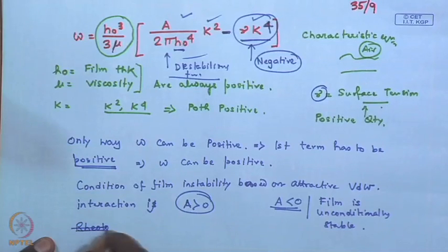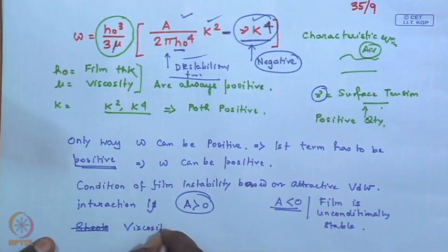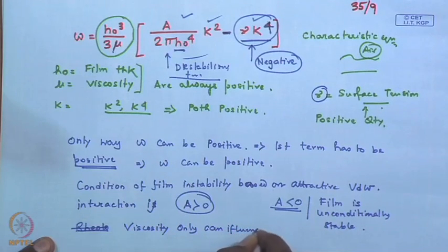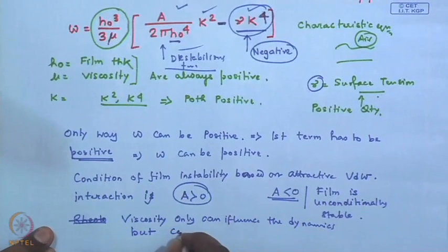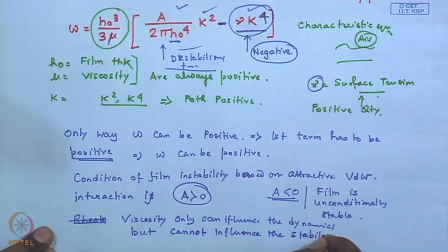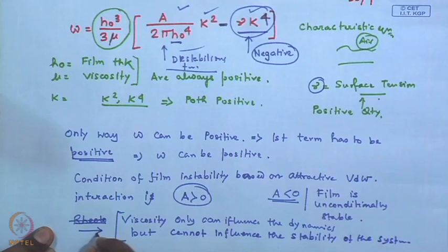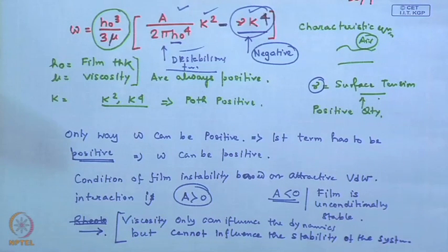That is, the rheology or the viscosity of the system can only influence the dynamics, but cannot influence the stability of the system. These are important findings that come out of linear stability analysis.